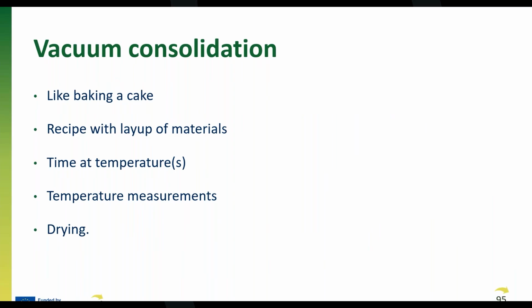So you more or less say it's like baking a cake at home. You have a recipe where you put your layup of materials, then you bake it at the time you have in the recipe, and the most important thing here is that you make the measurement on the materials in your tooling, not of the oven temperature or anything else, but on the materials. And one important thing is that you can actually incorporate drying in this process, so you don't have to pre-dry materials if that's necessary, which it often is when you are talking about biomaterials. Next one.